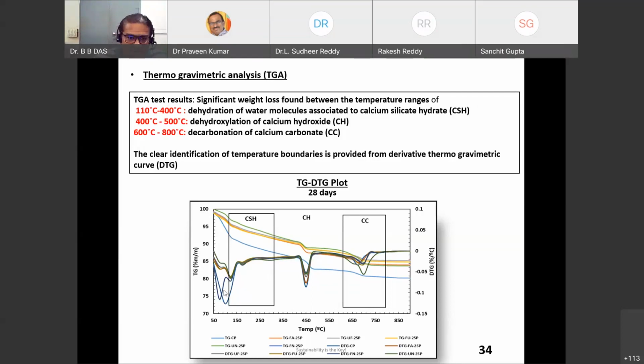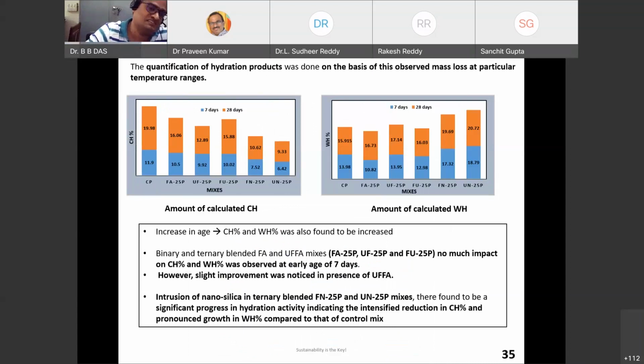So I have to consider only this zone if I want to know about calcium silicate hydrate. Similarly, we know 400 to 500 degrees centigrade is calcium hydroxide, so I have to adopt only this zone. Calcium carbonate is not part of this study actually, but those who work on the carbonation process have to hold this zone, 600 to 800 degrees centigrade, where you can see the decarbonation of calcium carbonate. Based on this, if you put into those equations I told you before in the experimental methodology, you can get the amount of calculated CH. Now this is the percentage. You can see the control and nanoparticles of all the mixes, and this is my percentage of calcium hydroxide.